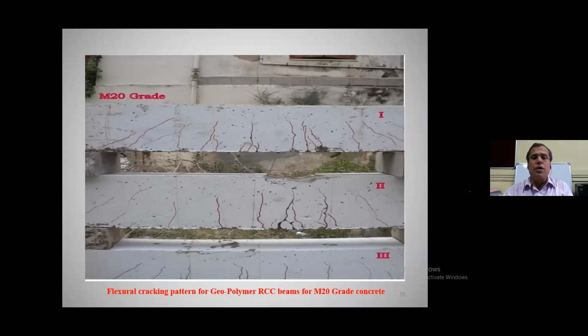It is a normal geopolymer concrete, but you can see the visualization of cracks is as good as your conventional concrete. Same, no variation, nothing. In fact, we found in some cases that natural concretes are having more cracks, abrupt cracks, but the geopolymer cracks are not abrupt cracks. They are very, very uniform cracks.